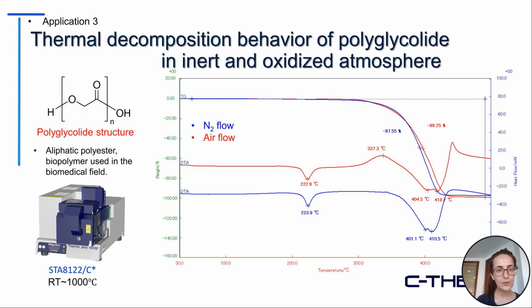The last example today that I want to explain is the thermal decomposition behavior of polyglycolide in inert and oxidized atmospheres. Polyglycolide is an aliphatic polyester biopolymer used in the biomedical field. The red curve is related to the polyglycolide in the airflow, and the blue curve is related to the DTA analysis of this sample in the inert atmosphere. The TGA curve shows a similar pattern for both samples.